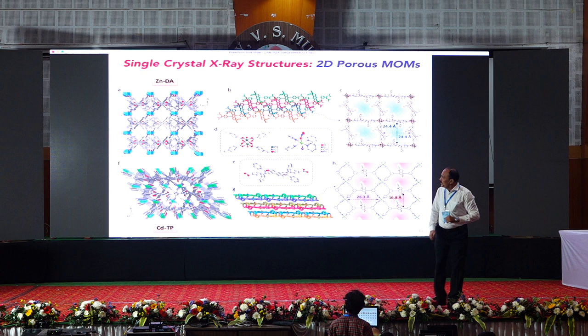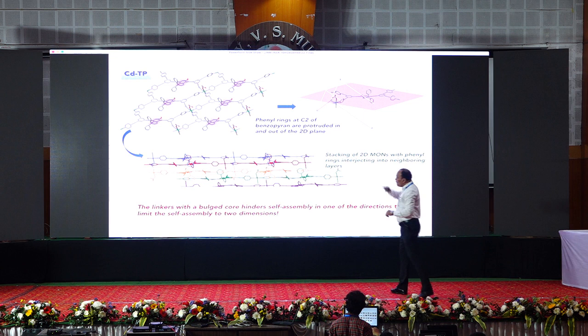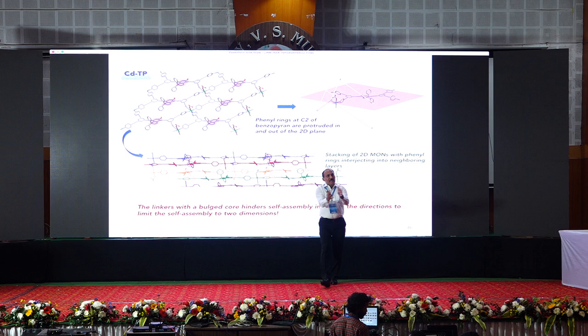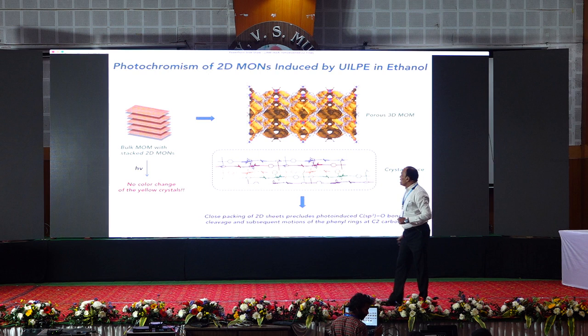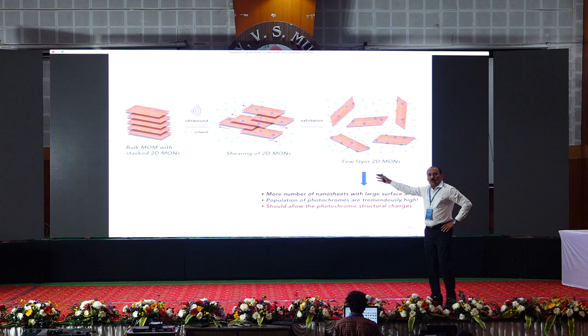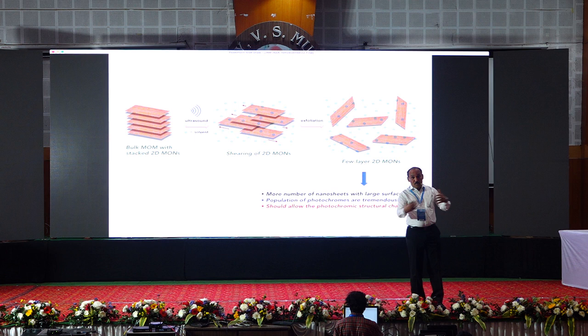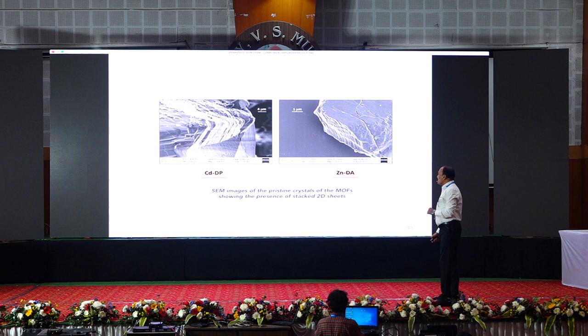So all these materials, if you look at the layers, this is how the layers are, and because the phenyl rings stick to each other, they're all compactly packed, there's no space. But if you liberate them, you will have the space. So this is what we expect, right? We expect that the layers, you put them into the solvent, ultrasonicate, you get this material, and this should show photochromism because you have built a photochrome into this 2D material, right? So this is what the material looks like.